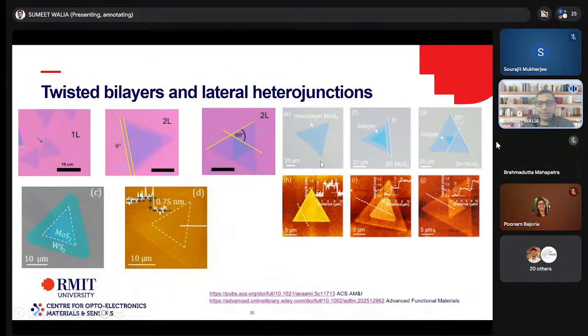So again, post that, we are also looking at growing different angles of bilayers. What you see up the top is 0 degrees and 60 degrees. We can go 30 degrees as well. Obviously, those who know CVD, we can't really control the angle at this point down to very small angle variations. So what we can do is an overlap of 30 degrees, 60 degrees, and with that overlap we see a stark difference in the electrical and optical properties. So I put the papers down at the bottom if you're interested.